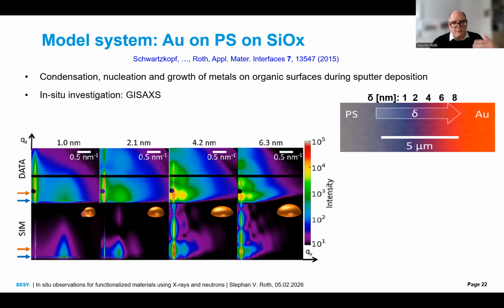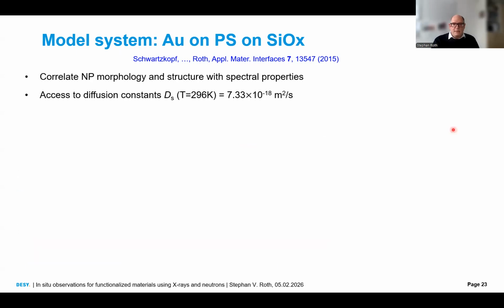When you let gold grow on polystyrene, it's no longer hemispherical, but in the beginning it's nearly spherical, then it becomes hemispherical at one point, and then the clusters become flatter and flatter, and in the end they touch each other and grow in height. And this change, when you produce a gradient, from pure polystyrene to the very thick gold layer, this is 8 nanometers of gold, you see a strong color change indicating the change of the cluster size and distance. And this is what we wanted to do.